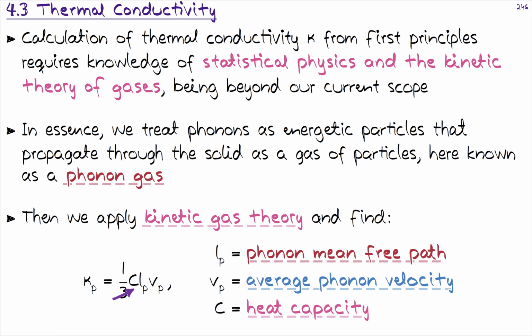And here, for example, we see that although diamond has a very low heat capacity at room temperature, so C is quite surprisingly low, I think it's around 5 joules per mole per Kelvin, and not very close to the 25 Dulong-Petit value, especially when we purify diamond, the phonon mean free paths can be increased. Especially the average phonon velocities are very high, due to the fact that the diamond lattice is mechanically very rigid, so that phonons propagate at very high velocities. So the speed of sound is very high in diamond.